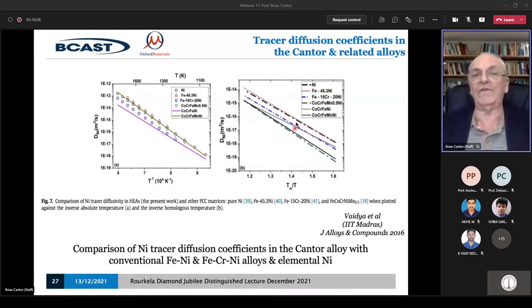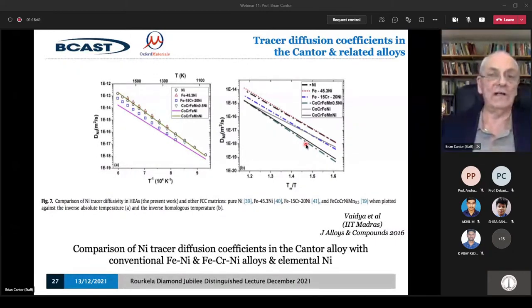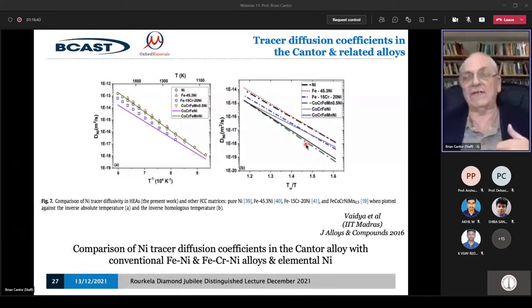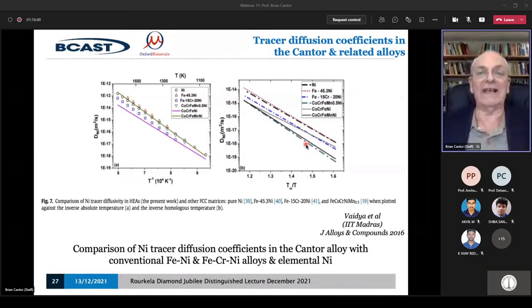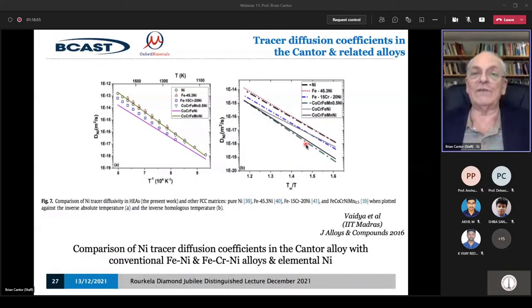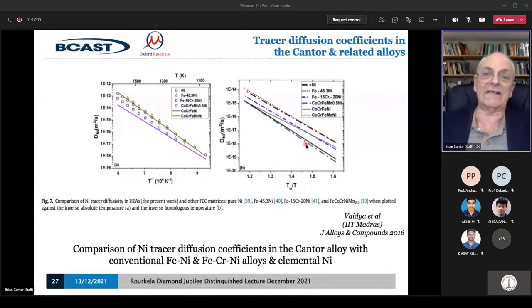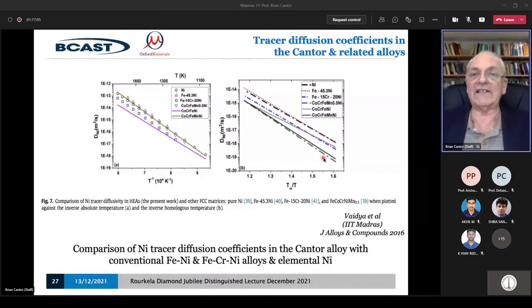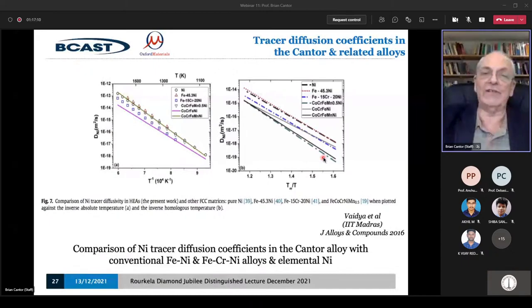This has very important effects, because the degradation of materials at high temperature, or under, say, radiation damage, is determined by the ability of the atoms to move around. It's the moving of the atoms around that leads to the degradation of the material. So these materials, not only do they have those great mechanical properties that I showed you, they're very resistant to degradation. I'll say more about that later. But that's the diffusion. That's the atoms moving around by vacancy hopping, by the movement of a point defect called a vacancy.